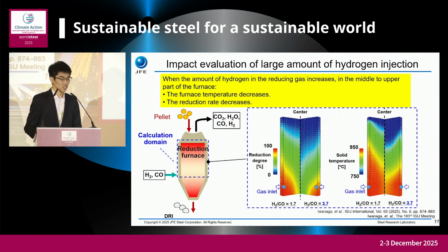In this example, it is shown that the reduction in the reactor is delayed by increasing the hydrogen ratio. The reduction degree in the center is lower, and this becomes more significant when the hydrogen content in the reducing gas increases. By increasing the hydrogen ratio in the reducing gas, the low reduction area is expanded in the upper part of the furnace. And because reduction degradation occurs in the lower reduction regions, it is assumed that reduction degradation is likely to occur when the hydrogen concentration increases. For these reasons, we thought that the endothermic reaction should be avoided as much as possible.